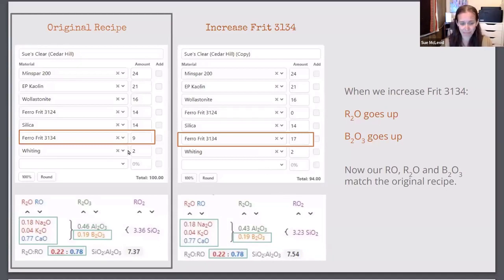So I know that if I increase Frit 3134, that will bring my boron level up. It also adjusts... 3134 has boron. It also has sodium, calcium, and silica, but I'm right now just concerned with the boron. So I increased the Frit from 9 to 17% just until the boron level matches. So now, in doing that, all of my fluxes match. That was just a happy accident. The fluxes match, the boron matches.